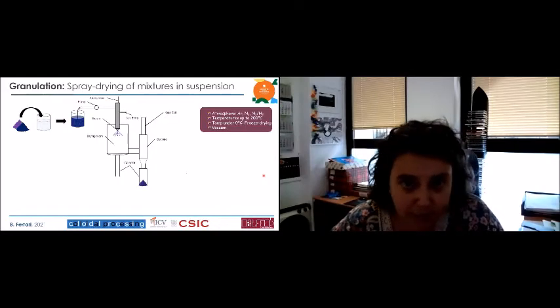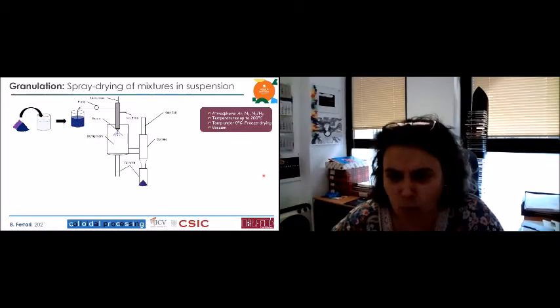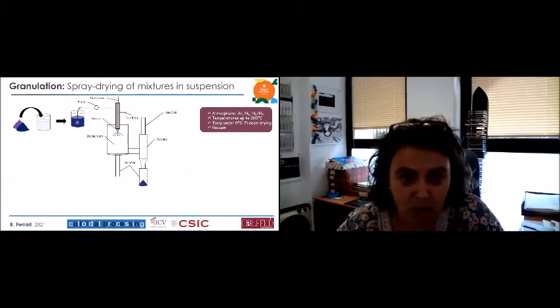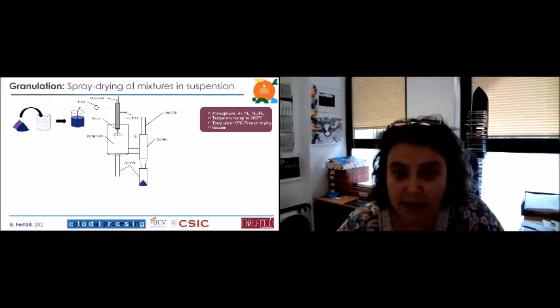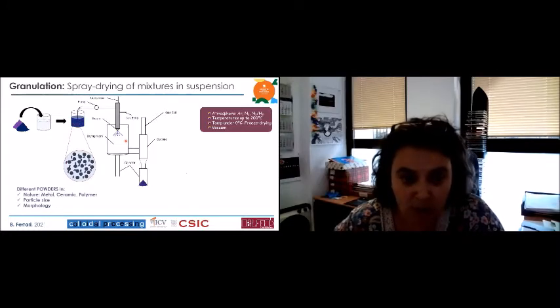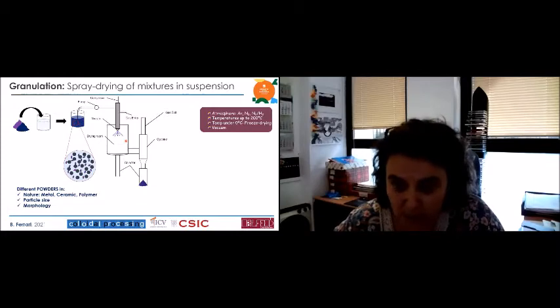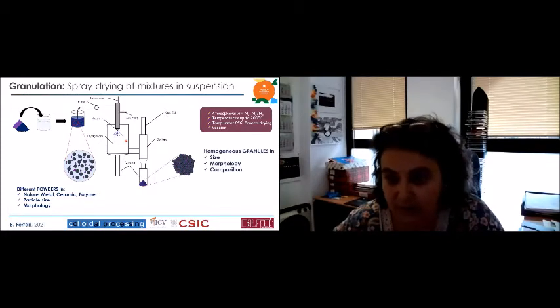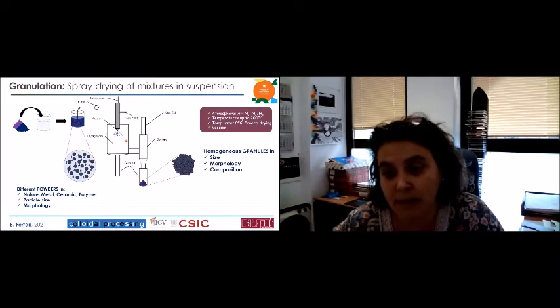So this spray drying technology is well known in ceramic. In the ceramic industry, everybody uses it. So we can prepare the suspension, mix together all the powder with your polymer, and in a drying room, you can make this kind of granules, right? It's very important to have a good suspension. It doesn't matter what kind of inorganic particle you are going to use, or what kind of particle size or morphology of this particle. And at the end, you are going to have these nice granules